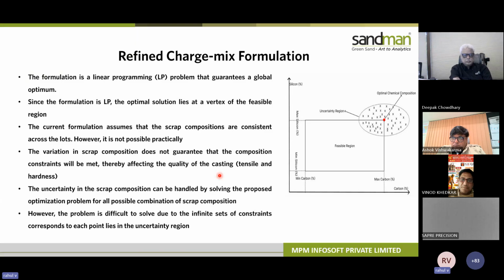So if I'm assuming that I'm going to produce a certain grade, and I think my carbon percentage in pig iron is just 4.2, but it turns out the actual chemistry was 4.5, then this data will totally mislead us and make our chemistry fall out of the specification limits. As you can see in the diagram on the right, this is the minimum and maximum carbon percentage that is allowed. And as our formulation is an LP, our solution will always fall at the boundaries of the feasible region. So when we design an LP problem and there is uncertainty, there is a very high chance that our solution might fall out of the target specification. All of this is caused by the uncertainty in the scrap composition.